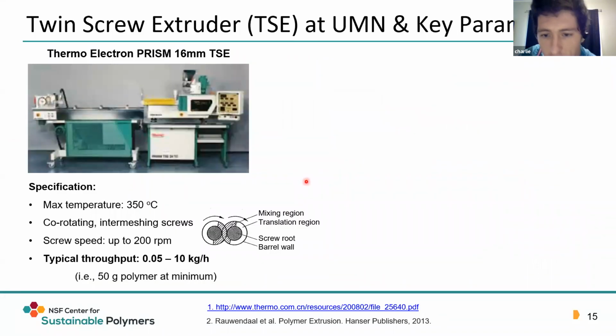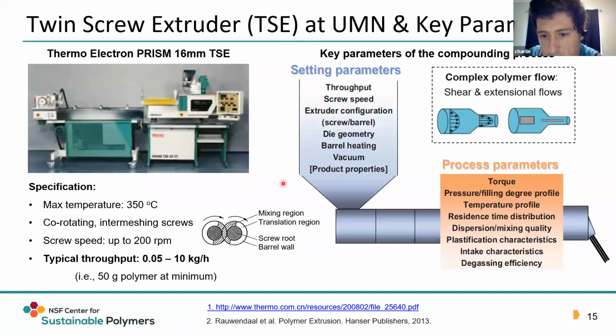The specific twin screw extruder we have at the U of M is a Prism 16 millimeter. It has co-rotating screws, and the screw speeds can go up to about 200 RPM. The throughput is about 0.05 to 10 kilograms per hour. A disadvantage of a continuous mixer of this sort is that you need a minimum of about 50 grams of polymer. Though this is an industrially relevant process and can produce blends very effectively at a large scale.